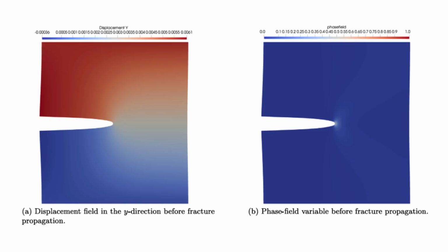Example 2. A square plate, but with a little notch cut into one side, then pulled in tension again. The notched plate, another classic. What were they testing there? Stress concentration. That, and comparing results to other published simulations, like from me and others, again, they got good agreement. But the really key insight here was about a simulation parameter the user has to set, the time step size. They used a pseudo-time delta t. The time step, how finely you slice the simulation time.